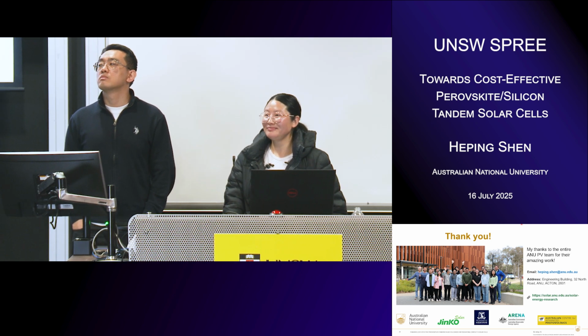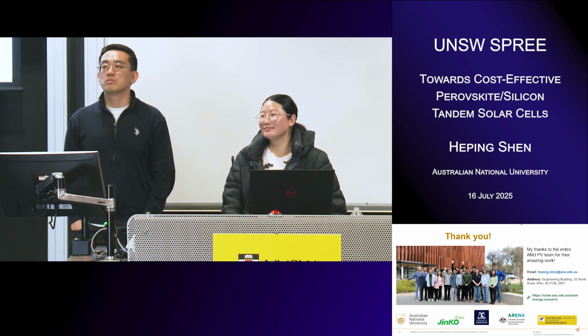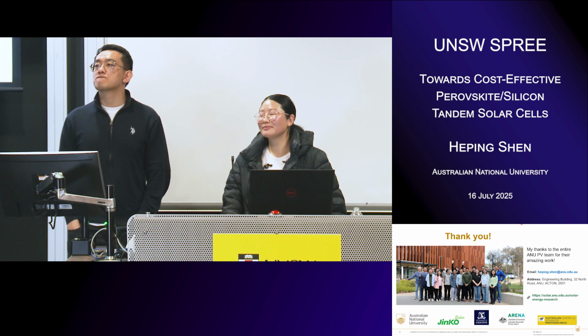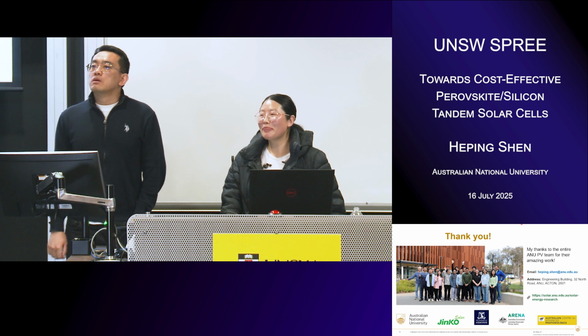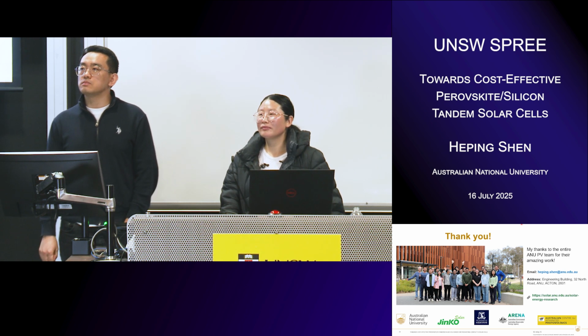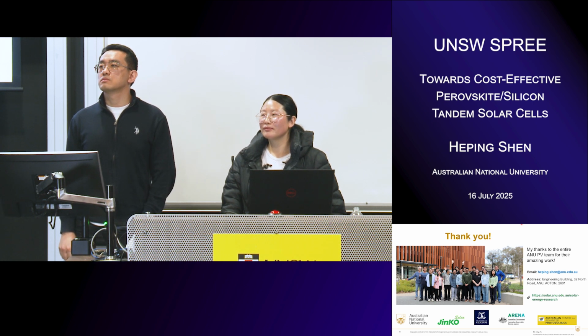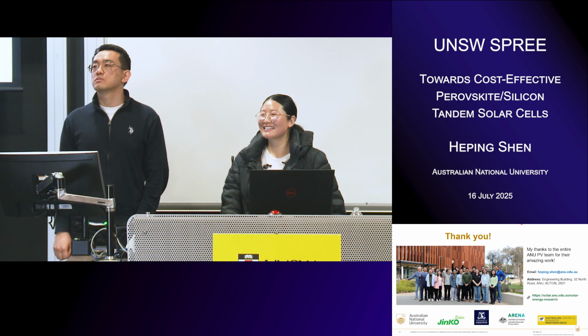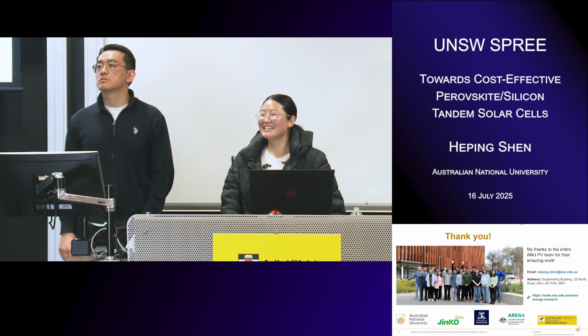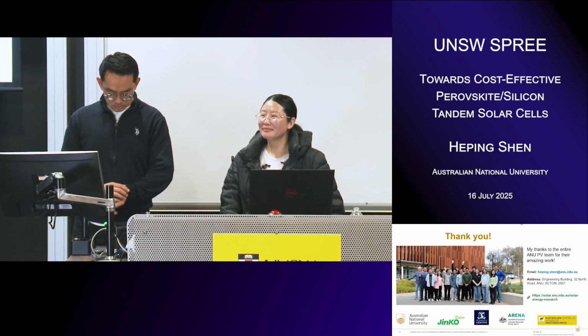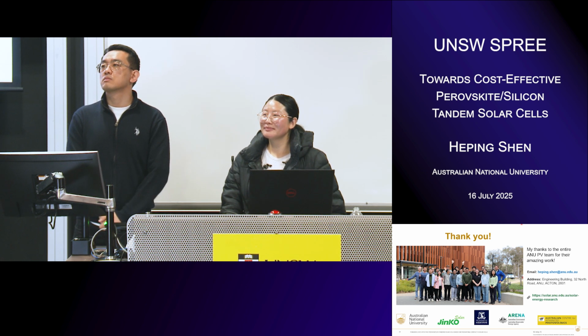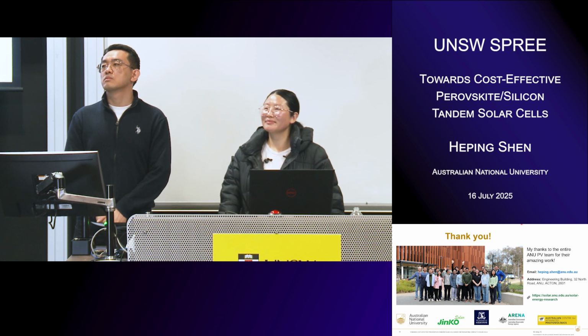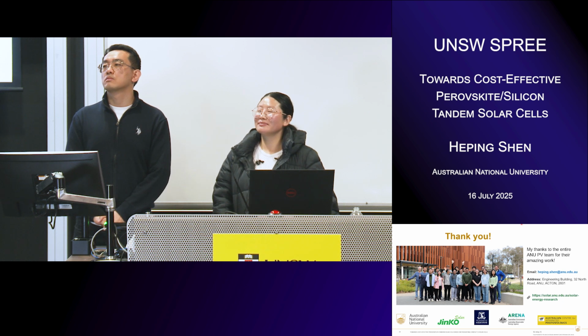Another question is, obviously over the years there's been a competition between the PIN and NIP. With NIP, for example, you use TiO2 or tin oxide for the electron transport layer, and for PIN, they end up using C60, as you mentioned. So it's tricky to look at which one is better, because for PIN they've also used self-assembled molecules, which is much better in terms of parasitic absorption. Whereas in your case here, you've used Spiro-TTB, same as Spiro-OMeTAD, as well as poly-TPD, which are, I guess, more parasitically absorbing. Are there any new materials people have come up with to use for the P-type hole transport layer?